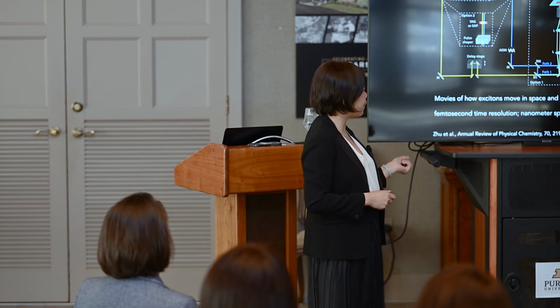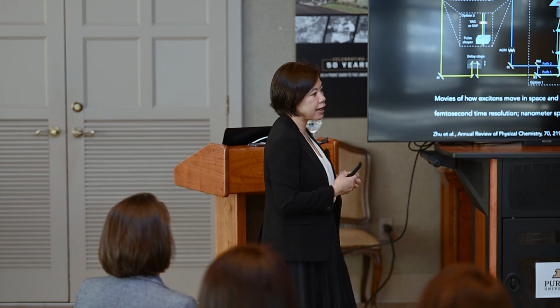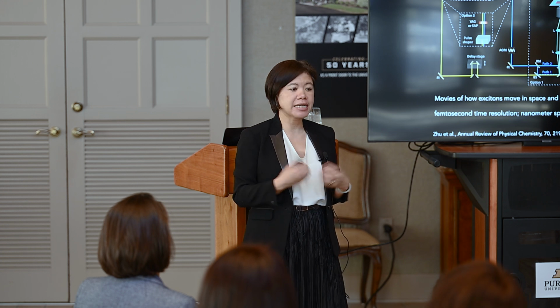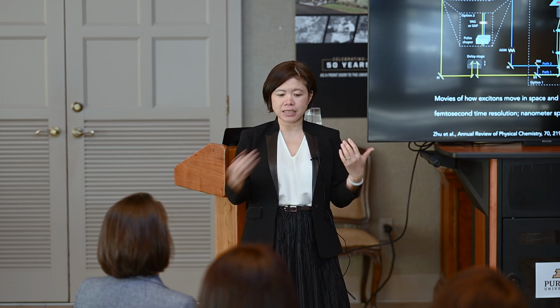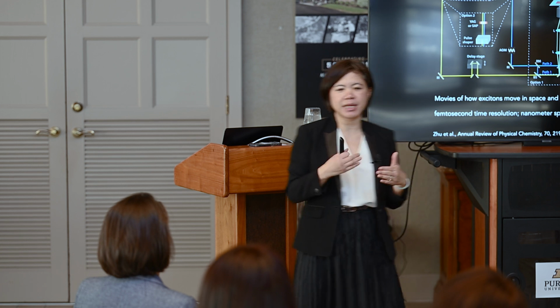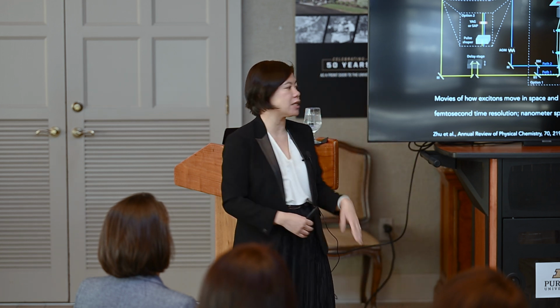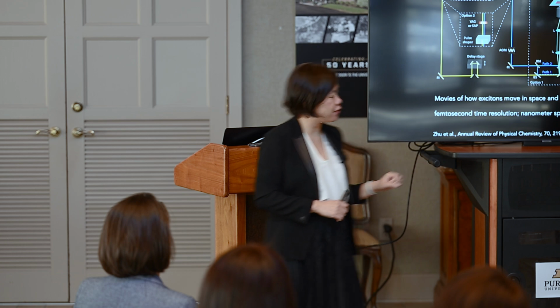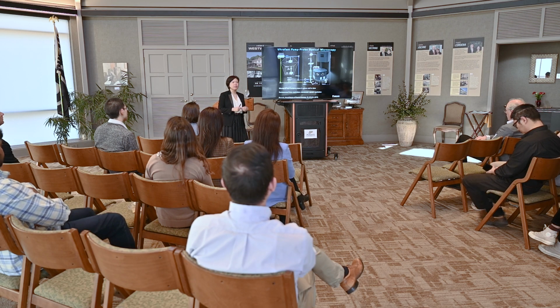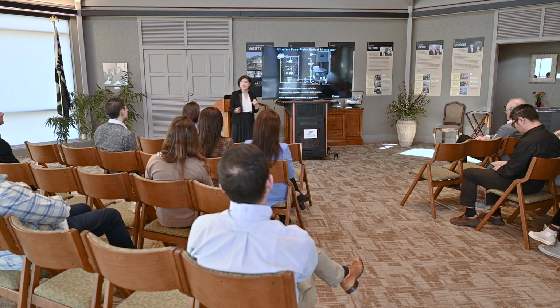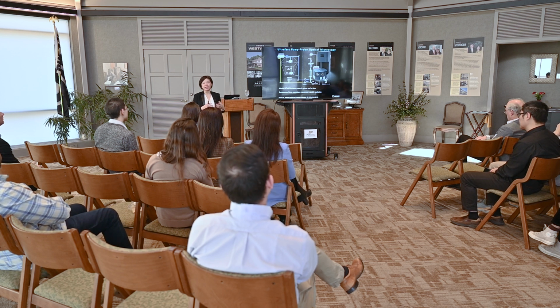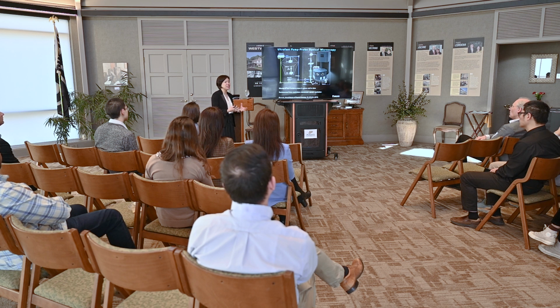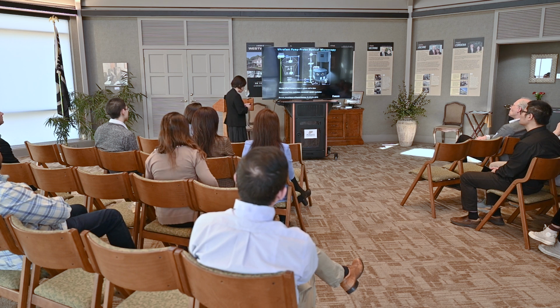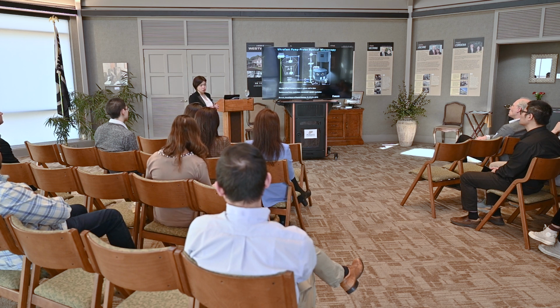It's very important to understand how these excitons become decoherent, because coherence, meaning that they are in phase, in step, is very important. So one critical thing we also do is look at temperature dependence, because it is a key factor in decoherence. This is the reason why currently all quantum computers are at cryogenic temperature: you need to freeze out all those dephasing and decoherence mechanisms. We can also do this measurement in a cryostat as low as 2 Kelvin.